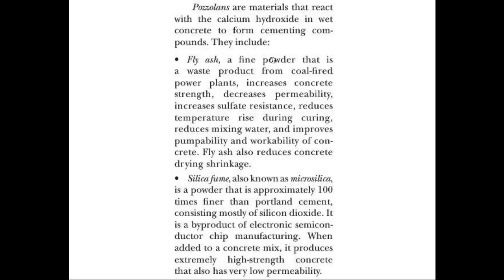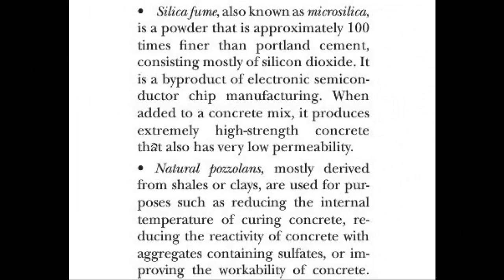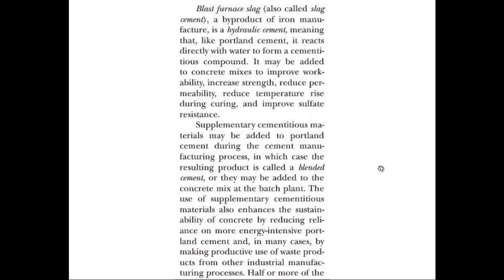Natural pozzolans mostly derived from shales or clay are used to reduce the internal temperature of concrete. Blast furnace slag, also called slag cement, is a byproduct of iron manufacturing. It is a hydraulic cement that reacts directly with water to form a cementitious compound, and may be added to concrete to improve workability, increase strength, reduce permeability, reduce temperature rise during curing, and improve sulfate resistance.